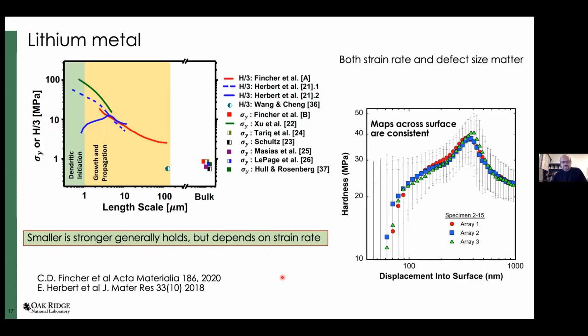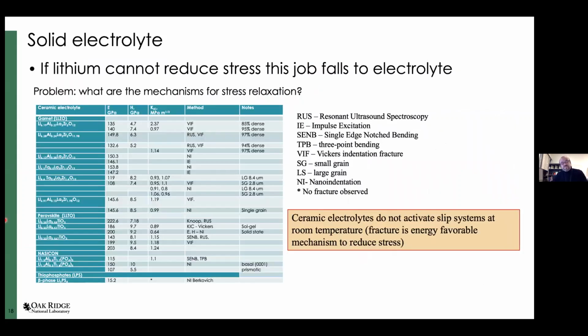Obviously, this depends on the strain rate, or you can say, on the applied current density, and it depends on the length scale as well. So what can be very ductile and very soft in bulk becomes extremely strong as you go to the smaller length scales, which are length scales that we encounter with lithium filaments that propagate.